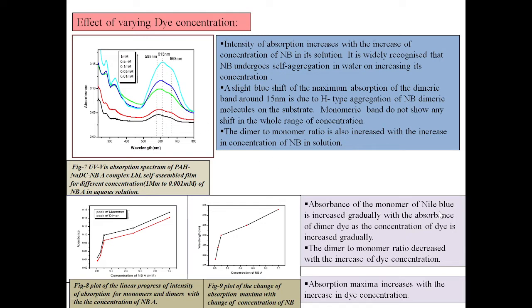The absorbance of the monomer of the Nile blue is increased gradually with the absorbance of the dimer dye as the concentration of dye is increased gradually. The dimer to monomer ratio decreases with the increase of dye concentration, and the absorption maxima increases with the increase of dye concentration.